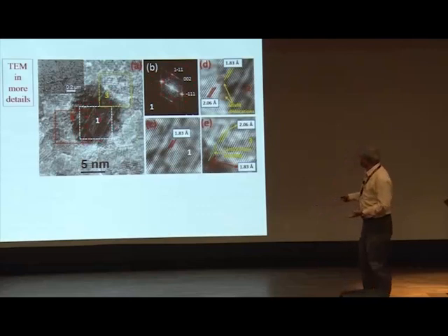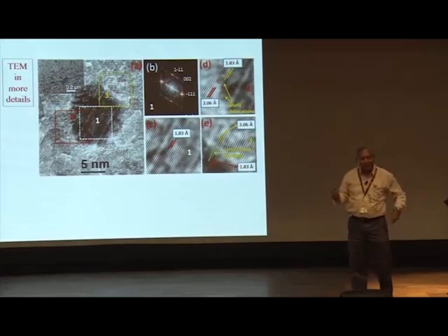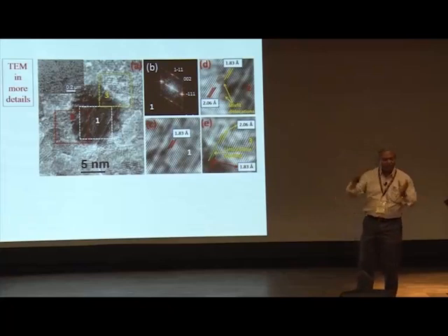This is an FCC pattern, face-centered cubic pattern. That's what we have. Second, if we take a high-resolution picture of that, we see here the 111 planar spacing is 1.83 angstrom. Now, if you look at the grain boundary regions, this and this, we see 1.83 within the grain, and at the grain boundary region it is 2.06. That's about 11% contraction. The grain boundary regions are not dense. The atoms have gone there and they have compressed the grains.